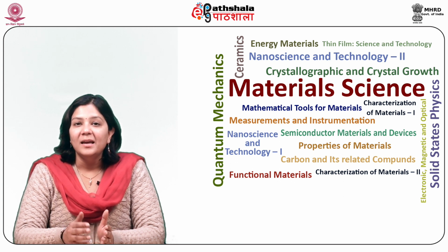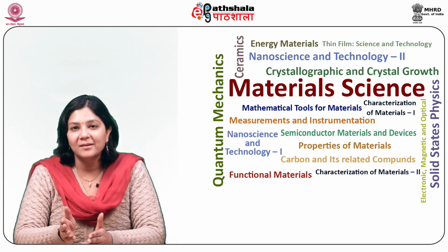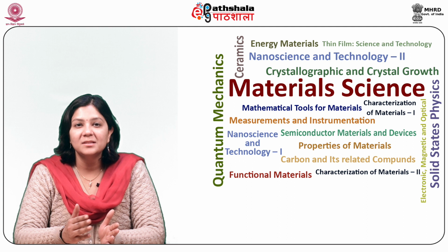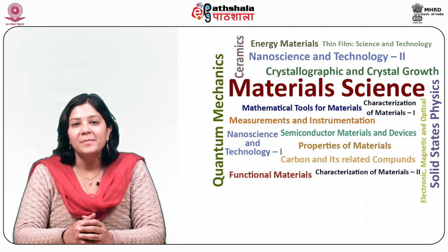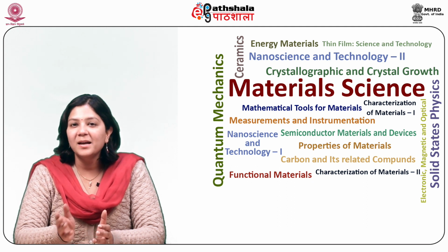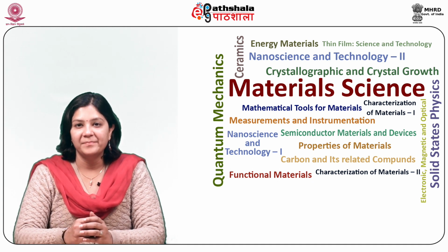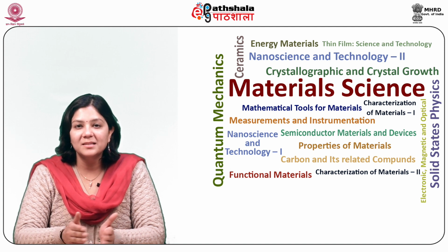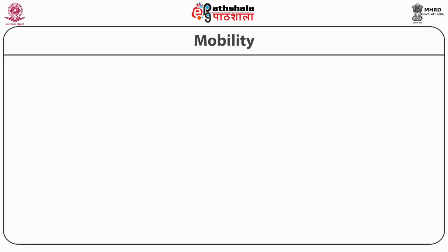Inelastic scattering. Inelastic scattering causes a significant amount of energy exchange. Like elastic phonon scattering, atomic vibrations cause energy band deformation. Optical phonons that cause inelastic scattering have energies between 30 to 50 milli-electron volt, while the typical energies of acoustic phonons are less than 1 milli-electron volt. The carriers undergo considerable variations in energy during the scattering process.